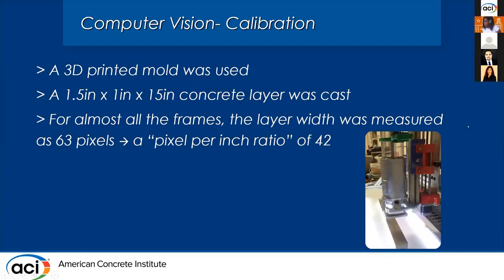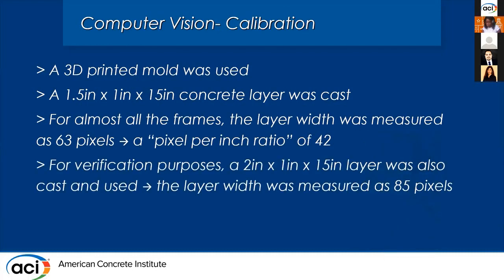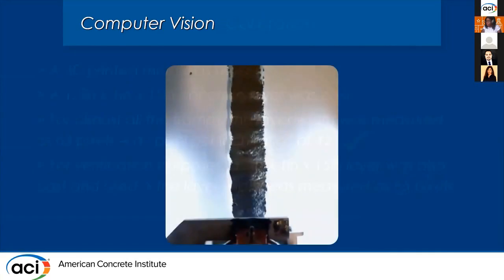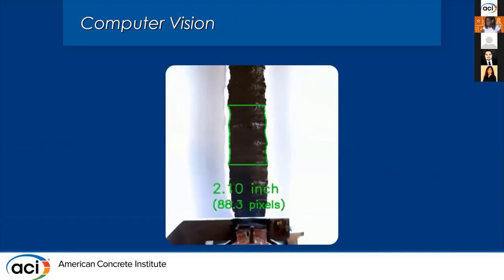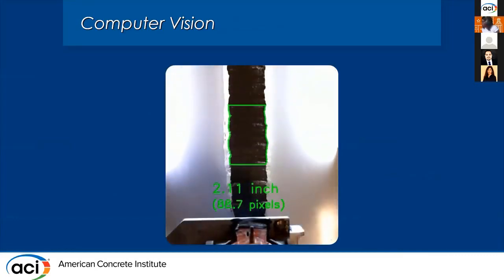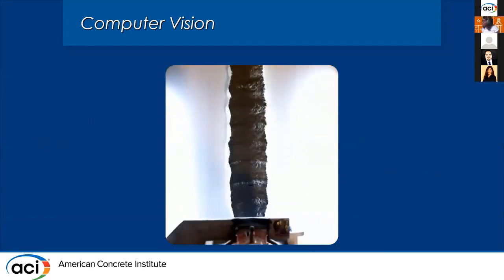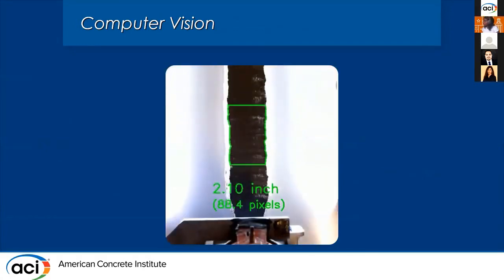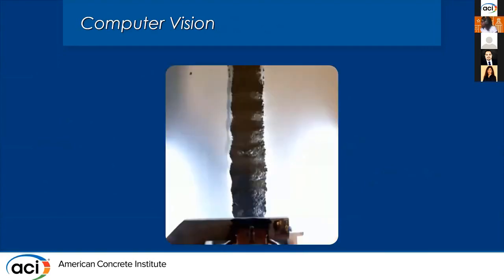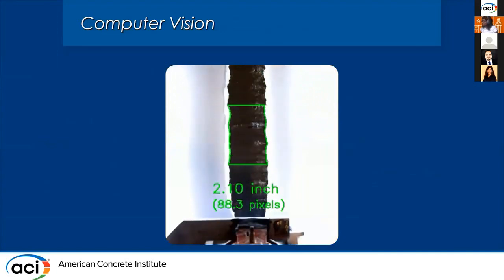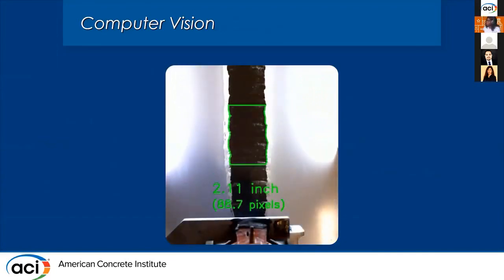And then to verify that, I fabricated another layer with a different width of 2 inch and used the system. This second measurement exactly verified the pixel per inch ratio that I selected and showed the high precision of my system before the main experiment. And here is a demonstration of the system for a case of over extrusion. Here the target width of the layer was 1.5 inch, but because of the over extrusion, the layer width was more than that. And as you can see, the system can measure that in real time and report the width of the layer.